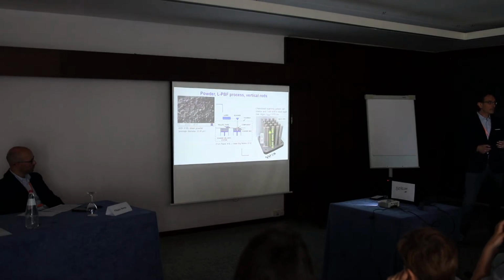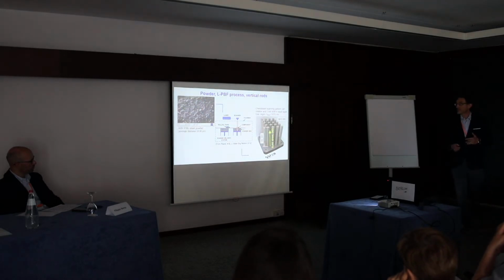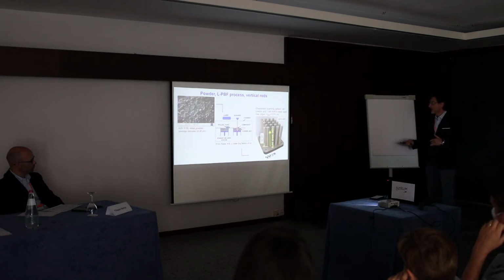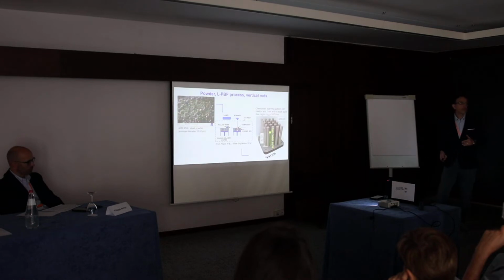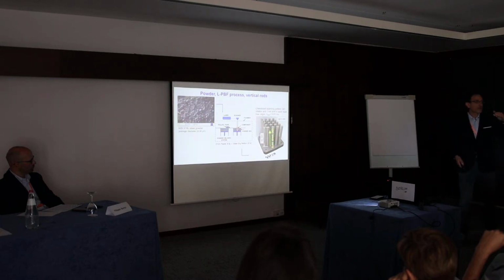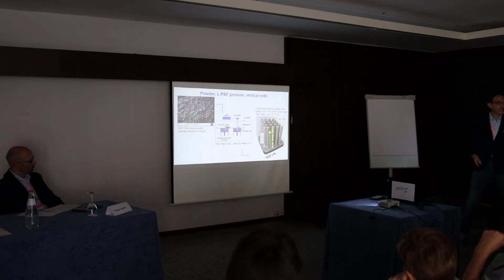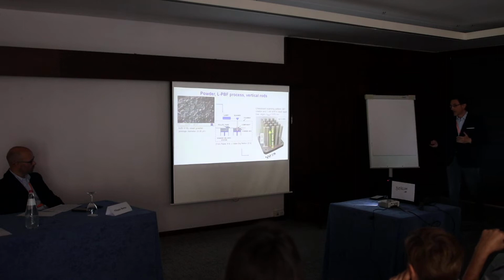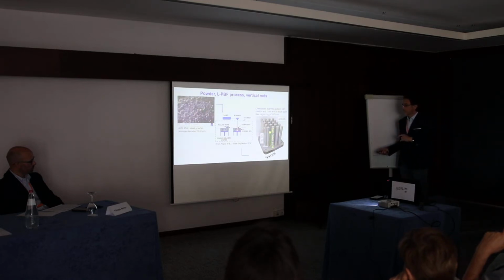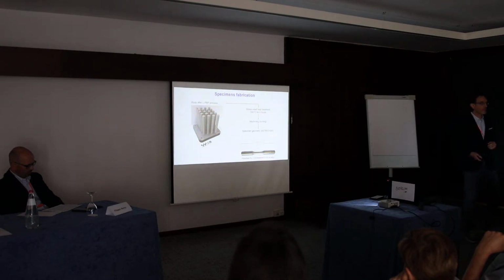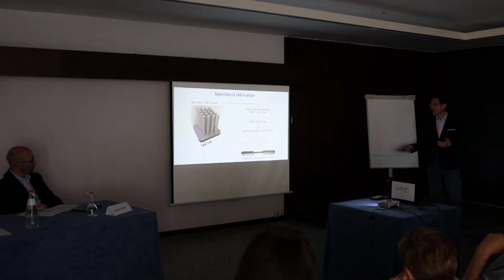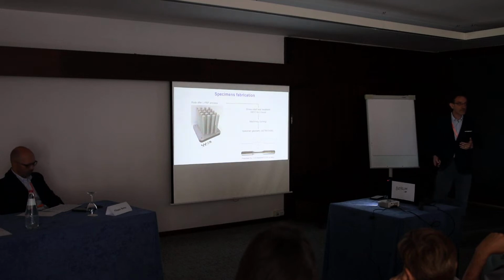We started with a powder of this material, then used a laser powder bed fusion process to manufacture vertical rods with length 180 millimeters and diameter 23 millimeters, using a chessboard scanning pattern. You can see here on the top there are different islands, and in each subsequent layer these islands are rotated 90 degrees in order to assure a more even structure. After that, we took these rods and performed a stress relief heat treatment, and then a machining process in order to obtain dog-bone specimens according to the standard.